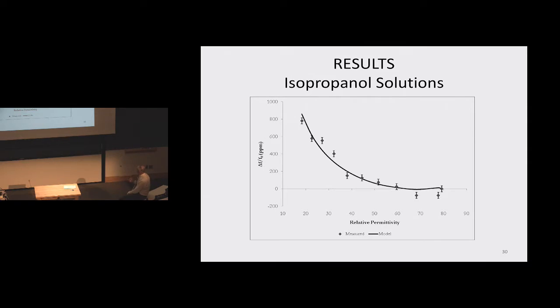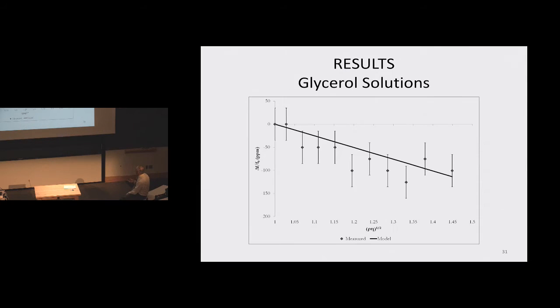The next slide is the results for the isopropanol solutions, which is the corresponding dielectric constant. Again, water is over here. This is the change in frequency. Again, the measured values and the model values indicate decent results. This corresponds to viscosity. The measurements are fairly broad in terms of the experimental measurements, but the general trend seems to be, in terms of the theory and the experiment, to show somewhat of a correlation in the results.